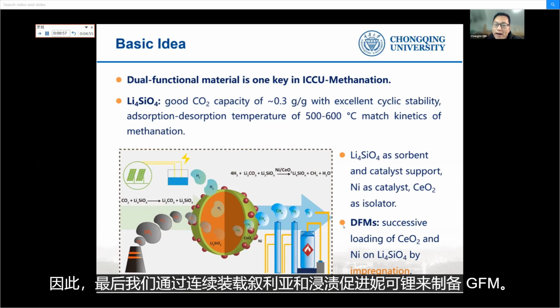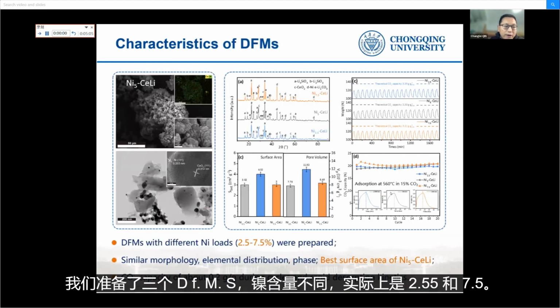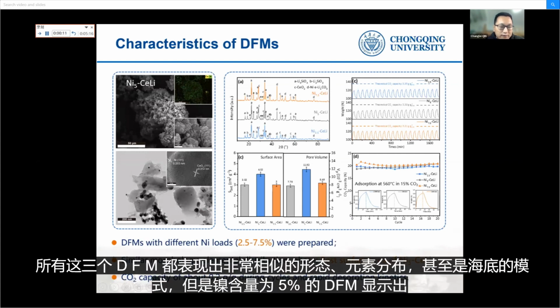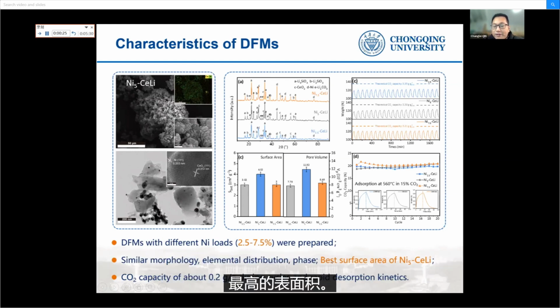So finally, we prepare DFMs by successive loading of ceria and nickel on lithium silicate by impregnation. We prepared 3 DFMs with different nickel loading, 2.5, 5, and 7.5. Actually, all these 3 DFMs show very similar morphology, elemental distributions, and even the phase patterns. But the DFM with 5% nickel has the highest surface area.